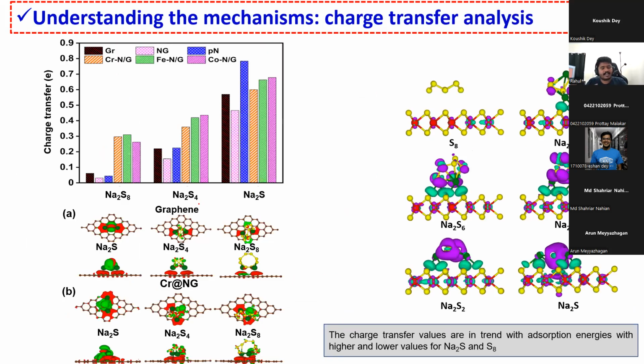Now we have calculated the charge transfer, basically how much charge is getting transferred between the systems. So this is the graphene and this is the single atom catalyst. You can see that the single atom catalyst has the higher charge transfer when compared to the other systems, and in particular you can see that Na2S has higher charge transfer when compared to other polysulfide adsorbed systems. That's the reason again why Na2S has higher binding energy when compared to other systems.